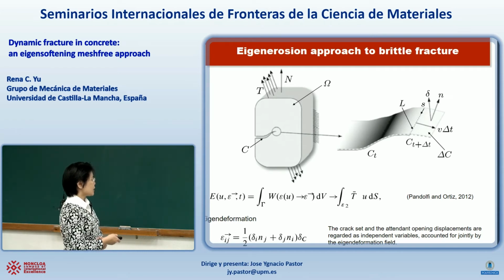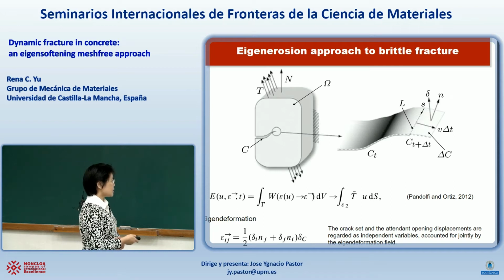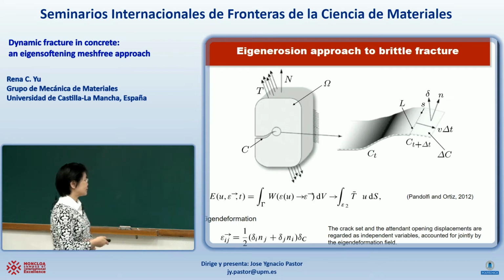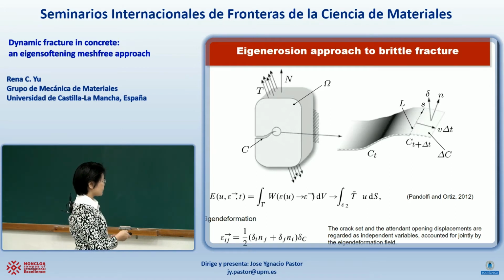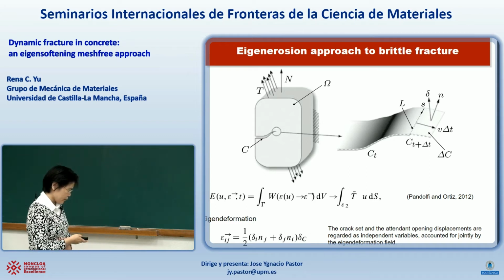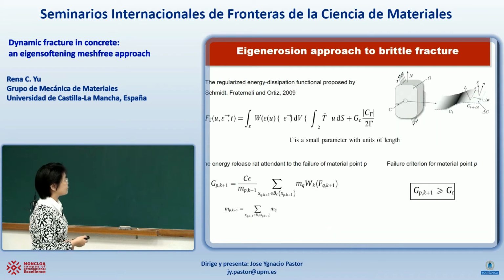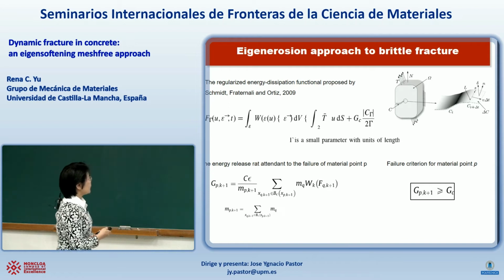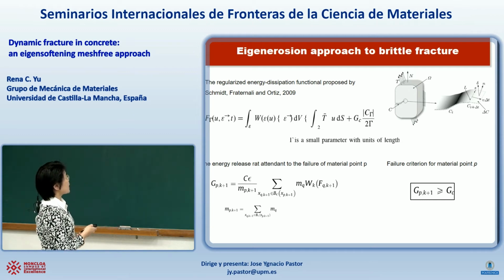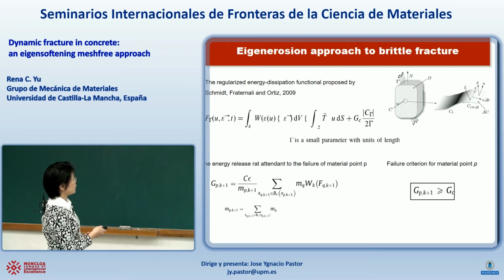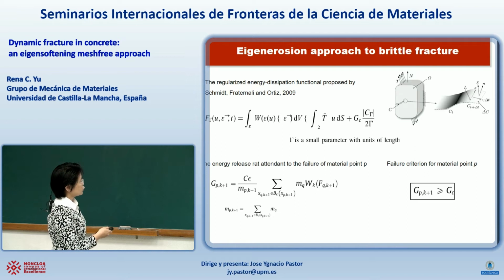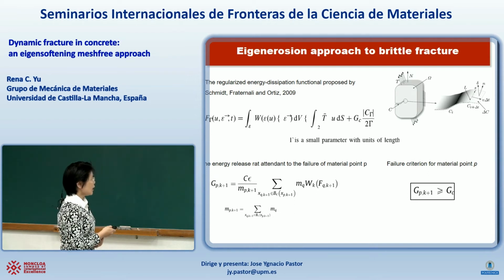So the idea is that the crack set and the attendant opening displacement, which is delta, are regarded as independent variables. In this case, they are both accounted for in this eigendeformation field. Since this would not cause local elastic energy, when we solve the minimization problem, we have a stress-free crack. And numerically, this is the work of Schmidt, Fraternali, and Ortiz in 2009, they use a regularized energy dissipation functional, which is defined as F. This is the previous energy functional. Now it is added with only two terms. This gamma here should be a small parameter epsilon, and this is the energy release rate.